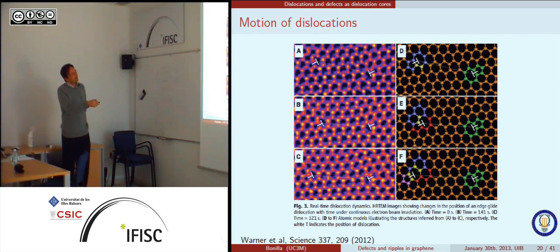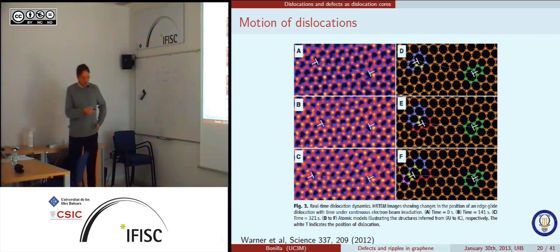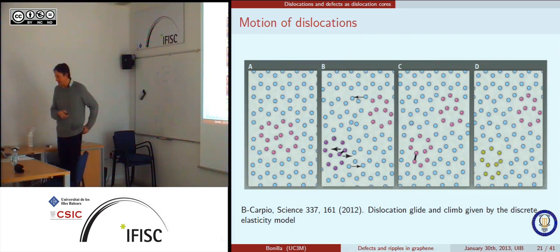So here the pentagon heptagon moves along the glide line one step. So this is glide motion. And now here, after a few seconds, this one moves in the perpendicular direction. So what happens here is that the electron beam has knocked off two atoms, and then this allows the dislocations to go against the Burgers vector in something that is called a climb. So this is climb motion. So in this work, they were able to report more carefully gliding and climb motion of the atoms in the graphene.